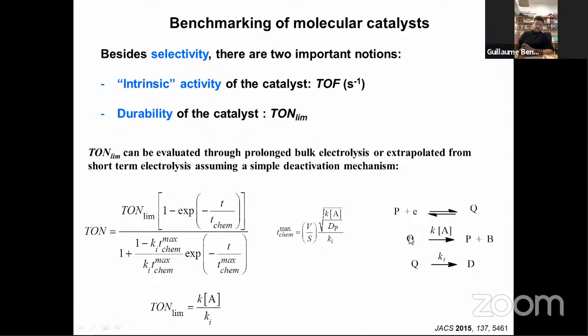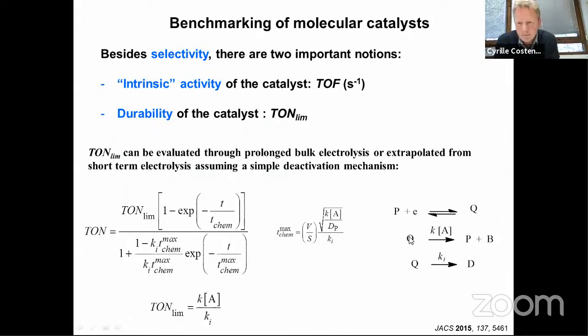I just wanted to have a precision regarding the crossing that you sometimes observe, which you spoke about earlier. I'm not asking for a full exposé on why this happens, but this is a little shady to me, and you gave some explanations 10 minutes ago. One possibility is that you have a process where you generate your catalyst, it reacts, and you make an intermediate, and maybe this intermediate might be transformed into a species which is actually more active, which means that as the reaction is going on, you are producing a better catalyst in the diffusion reaction layer. And so on the way back, okay,